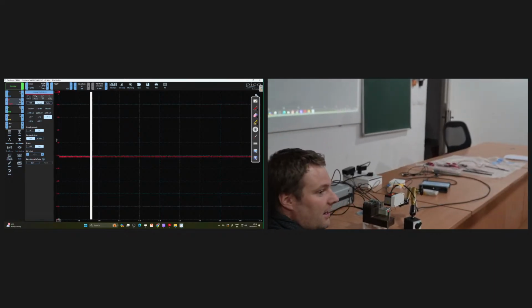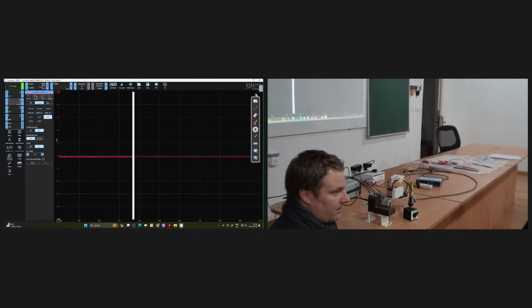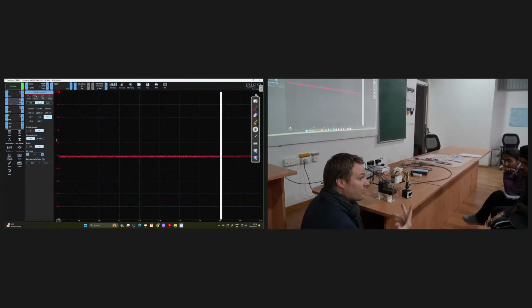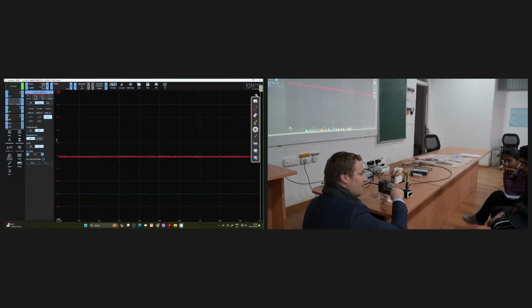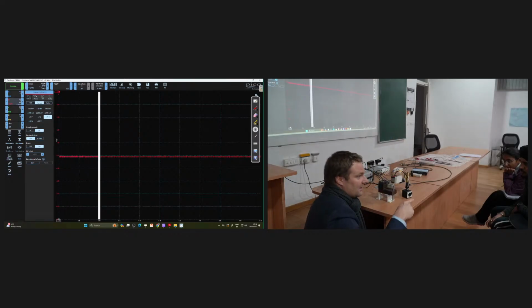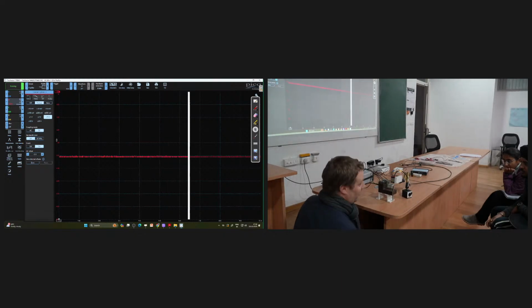So the next thing we do is a signal where we put first a high field on it, and then we do a negative field on it, and then a high field and a negative. So in the butterfly curve, or the butterfly diagram, we go from the left to the right, to the left to the right. And then what should happen ideally is that the elongation, which is the y-axis, does exactly what you should see. You should see the butterfly curve in the end. So let's hope that works. It's always a thing with experiments.